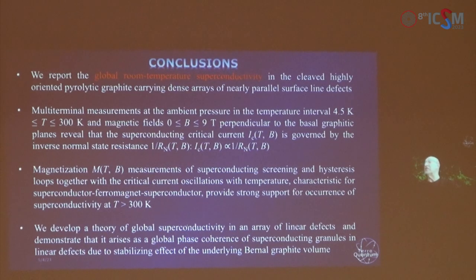which is basically characteristic for superconductor-ferromagnetic-superconductor Josephson structures. Basically the magnetization measurements of superconducting screening and hysteresis loops, with the critical current oscillations with temperature characteristic for superconductor-ferromagnetic-superconductor, provide strong support for occurrence of superconductivity at temperatures even exceeding room temperature and indicate that we should have superconductor-ferromagnetic-superconductor Josephson junctions. And we develop a theory of global superconductivity in an array of linear defects and demonstrate that it arises in global phase coherence of superconducting grains in defects due to stabilizing effects of the underlying Bernal graphite bulk.